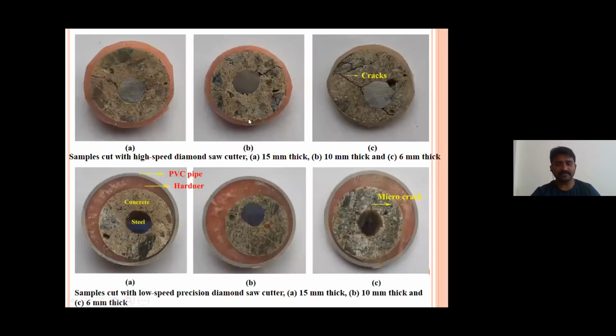So this is the physical observation, or as you can say, eye observation. If you see the top portion, it is for high speed cutters, and the bottom three are for low speed cutters. The A part indicates 15 mm thick sample, B part indicates 10 mm thick samples, and C part indicates 6 mm thick samples. See, for 15 mm thick with high speed cutters, we were able to observe a few cracks. For 10 mm, the crack is widening, and for 6 mm, see, a lot of cracks.